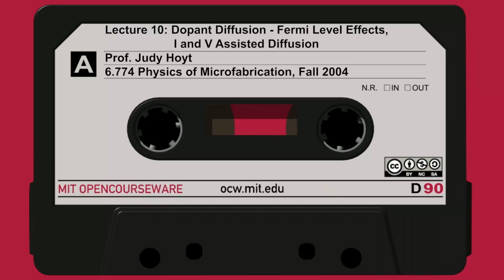This is the calculated, sort of theoretical line, where they use this type of expression. So the effective diffusivity was given by a constant, d0, plus d minus times n over ni, plus d double minus times n over ni squared. So there are three terms here. And what this equation tells you is, if I plug in n equals ni, then it becomes a constant. At ni or below, this whole thing goes to a constant number. And so if you go below ni, indeed, the diffusivity is approaching a constant here. It looks like about 1.5 times 10 to the minus 14th.